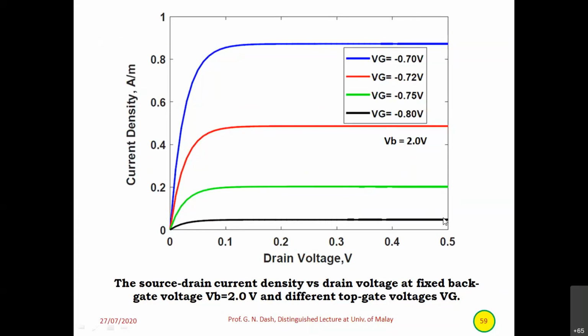If VG is changed from -0.70 to -0.72, you can see the saturation current drastically reduces. Then -0.75 further reduces it drastically. So this saturation current is extremely sensitive to the change in the gate voltage. Therefore, the gate can be very suitably employed to control the current, and you can also keep a very good on to off ratio by this process, by the Nanoribbon GNRFET.